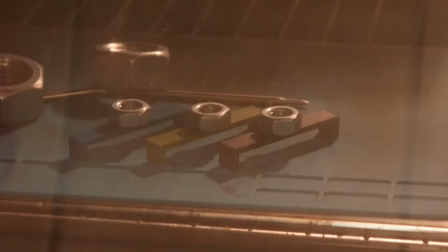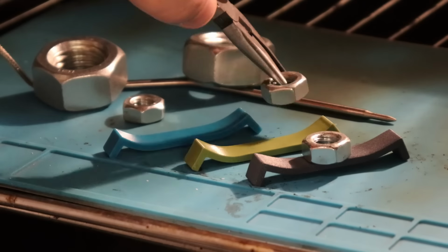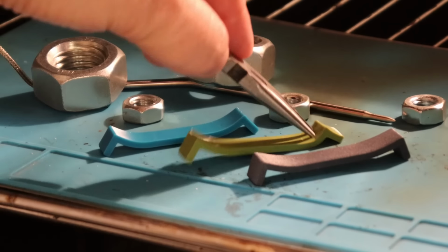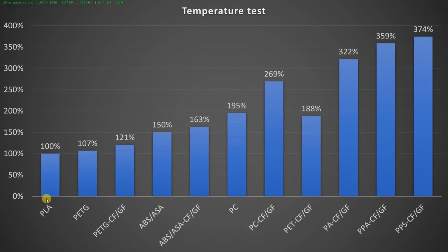Temperature test in the oven. M10 nut as a small load. And I'm recording the temperature of the first noticeable deformation. And we can see another weak point of the PLA. It will start to deform at 50-55 degrees Celsius. PETG at 65-70, ABS-ASA around 90.